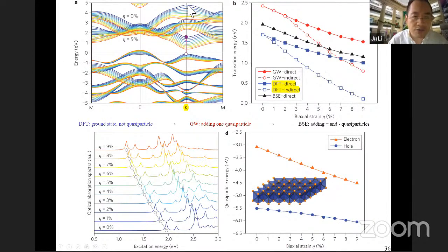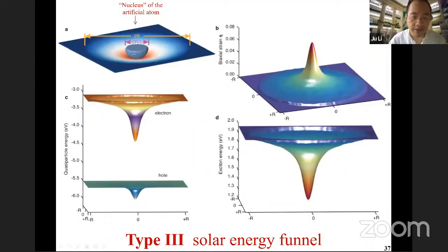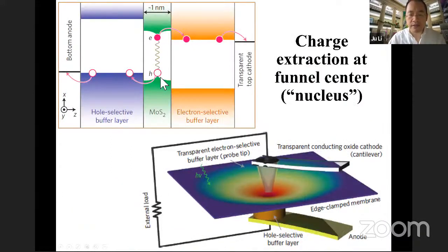And here are the calculation results. So this is the electronic dispersion as a function of strain. This is the optical absorption spectrum from 0 to 9% strain. It shifts from something like 2 electron volt to close to that of silicon, 1.1 electron volt. And then from the band alignment, it's either type 2 or type 3 solar energy funnel. We believe it is type 3. In fact, this is an artificial atom. You renormalize the divergence because it's not infinitely sharp. There is like a nucleus to this artificial atom. And you can use this to absorb different colors of the solar spectrum.